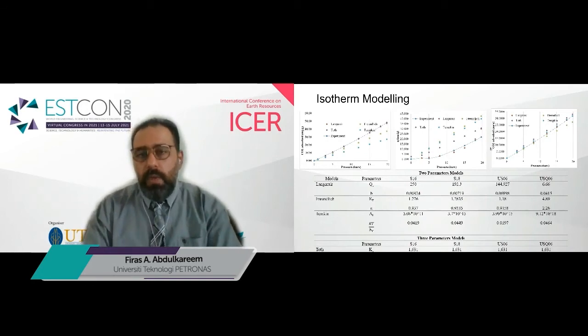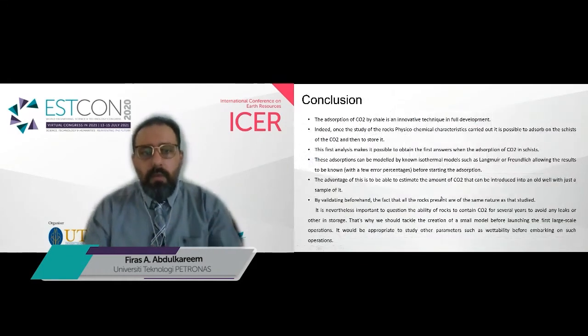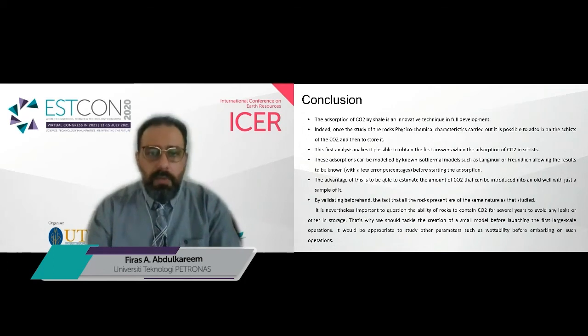And at the same time, we have some homogeneous contribution with some accumulation on the shales' active functional groups. From that, we can conclude that the adsorption of CO2 on shale is actually an innovative technique in full development. If it is fully applied in the reservoirs, it could bring a total reduction in the utilization of water in hydraulic fracturing, to enhance the methane or hydrocarbons desorption and production from the unconventional reservoirs and the natural gas trapped in the subsurface reservoirs.